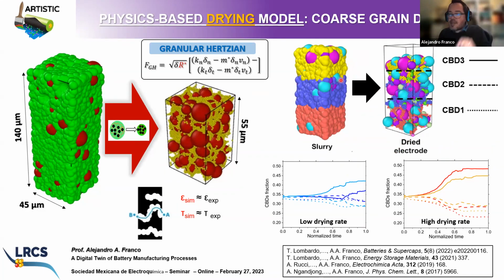When you shrink the CBD at different rates, by playing with the rates of shrinkage of these different CBDs at different zones, you can converge to electrode microstructures with carbon binder domain, with also solvent in this case, with different repartitions along the electrode thickness. And in particular, if you apply high drying rates, you will start to see a lot of gradients of CBD content along the electrode thickness, in good agreement with what we can find at the experimental level.